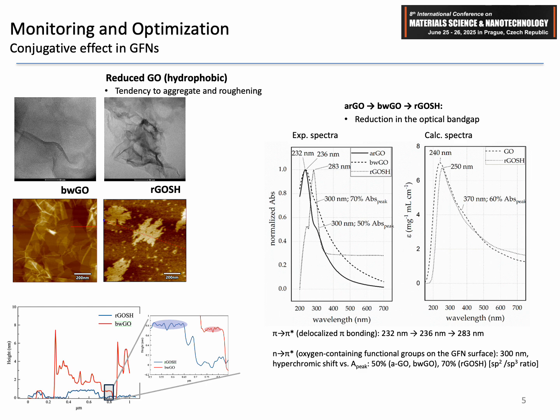In the pristine graphene, we observed the characteristic absorption peak at 230 nanometers, which corresponds to the pi-pi star transition of the conjugated carbon bonds in the backbone, and we can follow a progressive red shift and broadening, with a decrease in intensity, going to the base-washed GO and then to the RGO-SH, with a concurrent change in the band in the shoulder around 300 nanometers, which is the n-pi star absorption. This also changed the relative intensity compared to the peak, from 50% for the pristine and base-washed GO to 70% for the reduced thiolated GO.